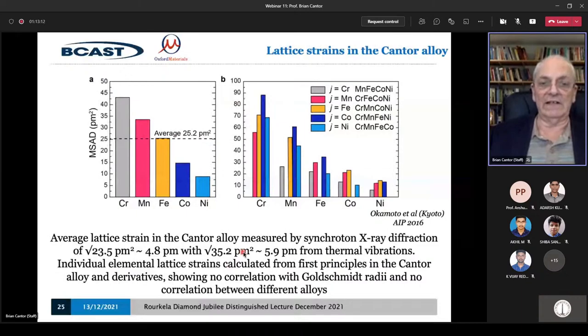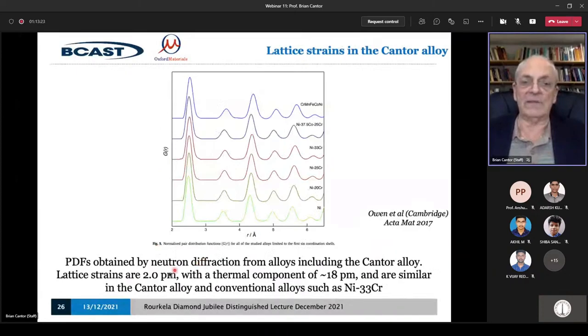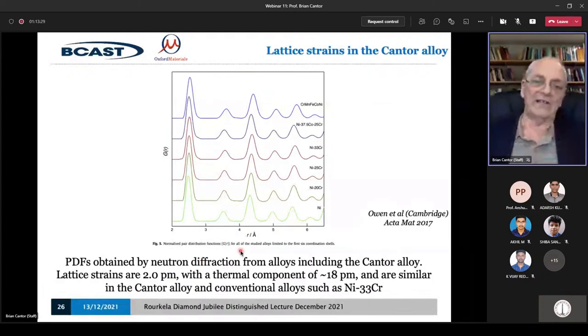Well, in the five component Cantor alloy, it's been measured by synchrotron X-ray diffraction to be 4.5 picometers, just under 5 picometers, and by neutron diffraction to be 2 picometers. So it's in the right order. So we can think of it like this. There are a few picometers of strain from point to point in these materials. And that leads to significant variations in physical properties throughout a material, going up and down on a scale of about 20 microns, if not more. You need a big chunk of material before you average over the whole of that variation.